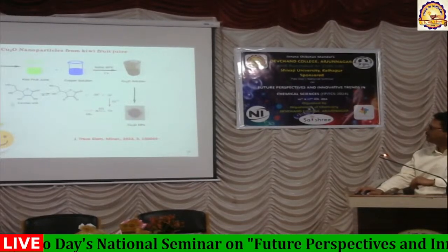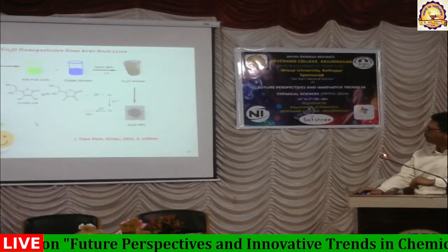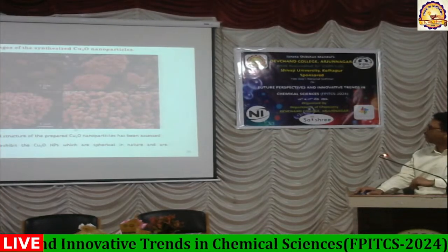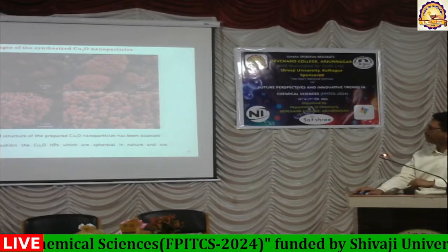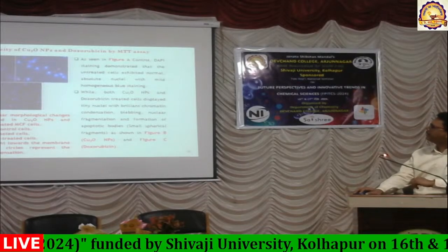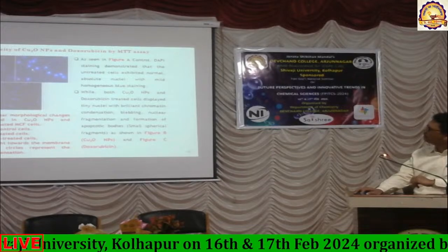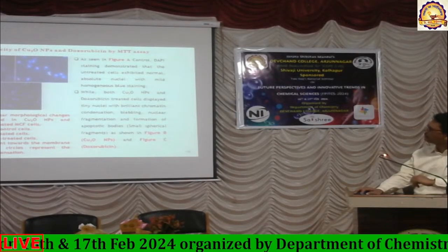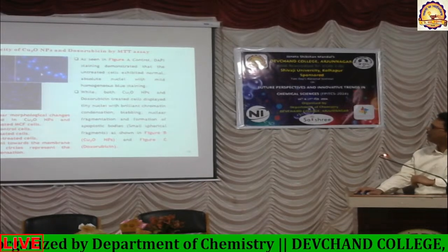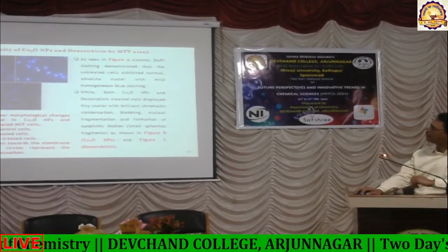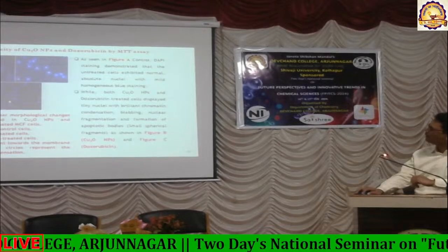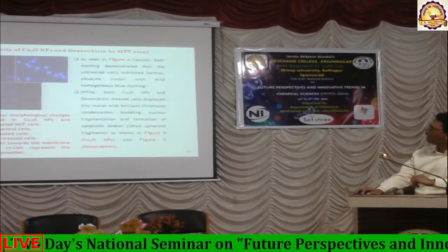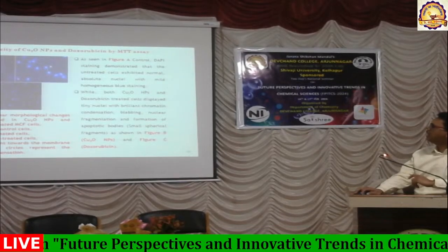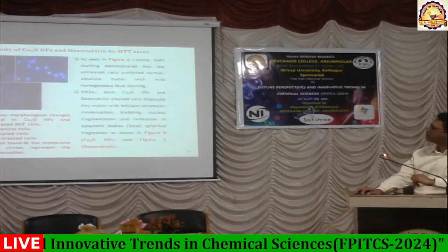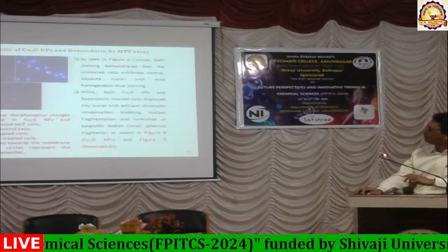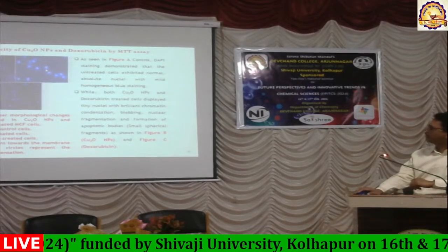This is the mechanism of conversion of copper sulfate into nanoparticles. And this is the FESEM image of this copper nanoparticle, which is globular shaped, and this is the characteristic pattern of copper oxide nanoparticles. And the application that we did was the cytotoxicity, where these were introduced into cancer cells, and we found that there is blebbing, meaning the chromatin of the nucleus has come out. This is the normal untreated, and this is doxorubicin, which is an anti-cancer molecule, and these are the copper oxide nanoparticles which we introduced, and the cytotoxicity of copper oxide nanoparticles is clearly visible, which will exhibit its toxic effect on the cancer cells.